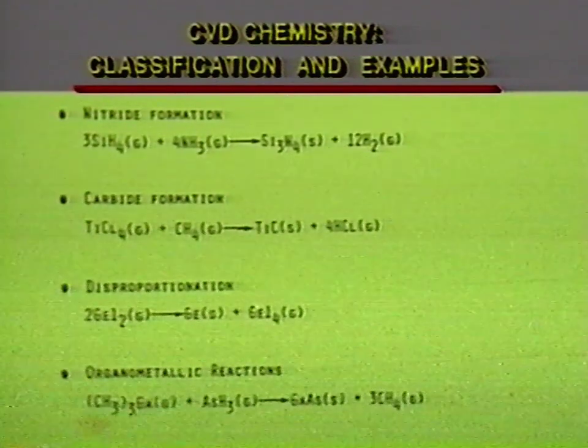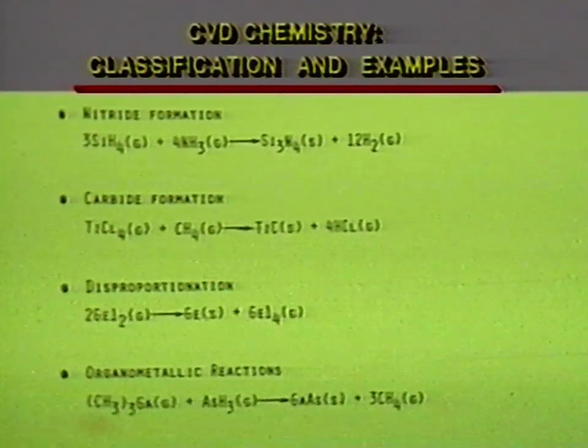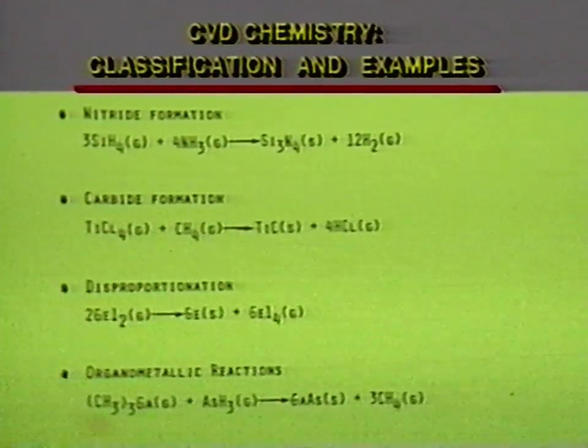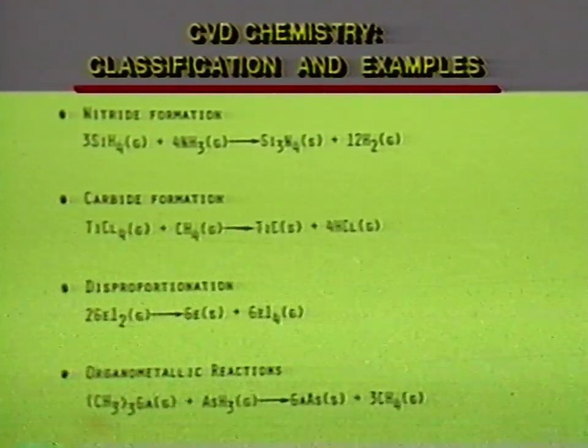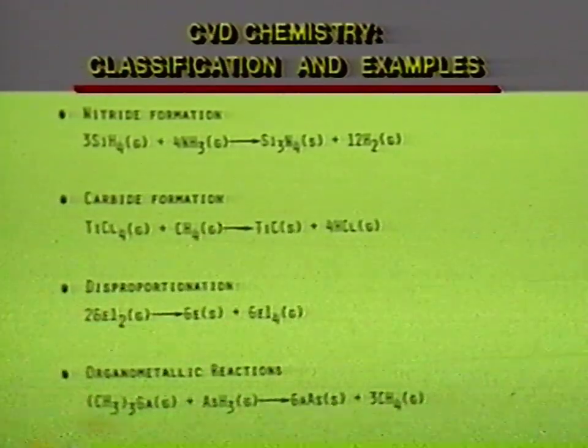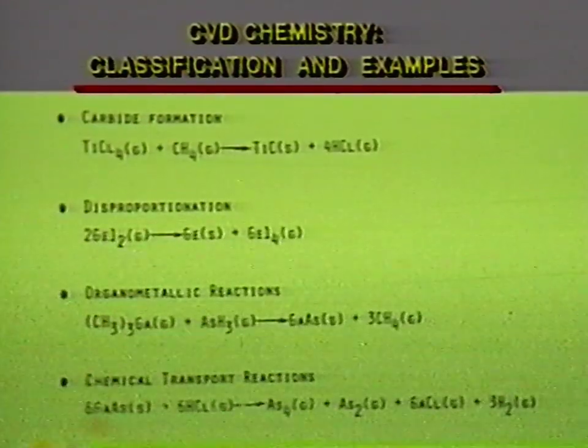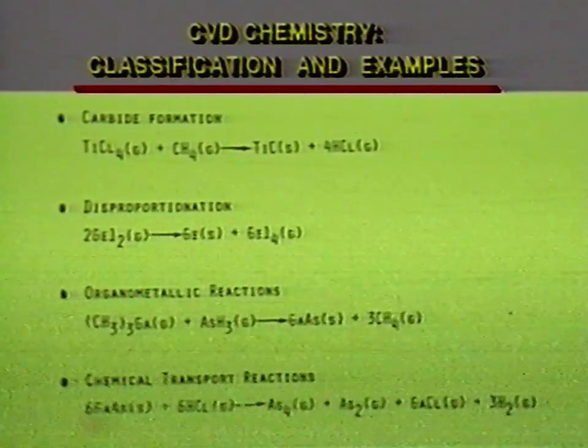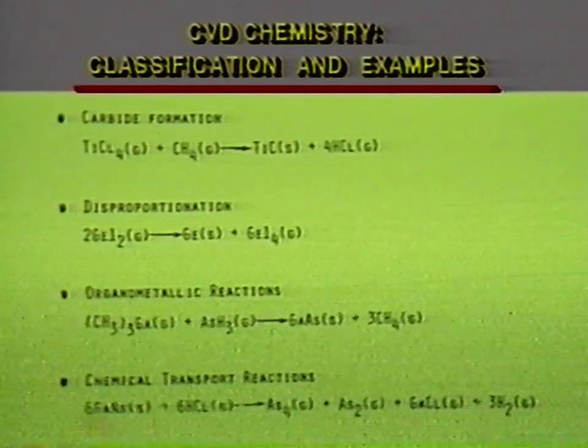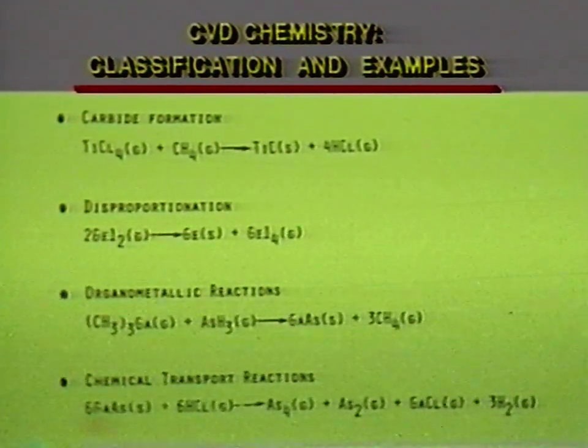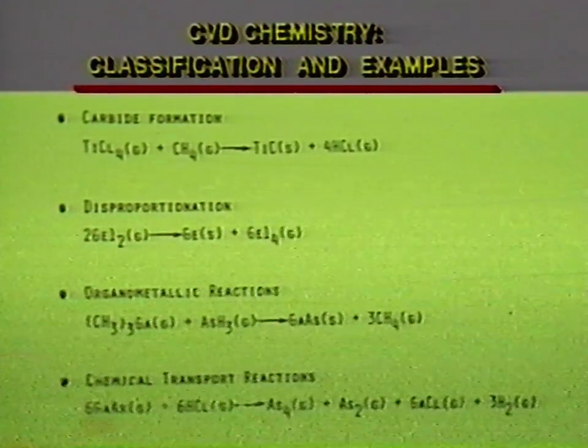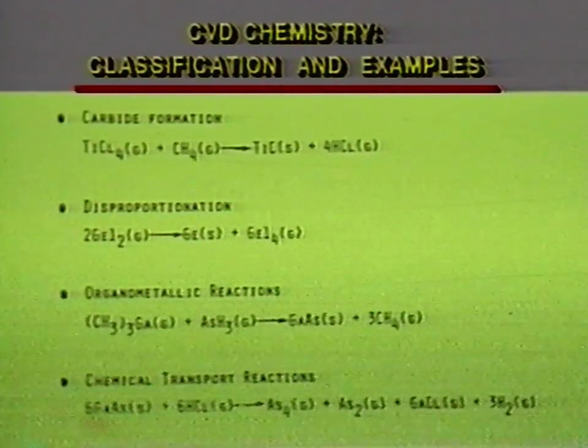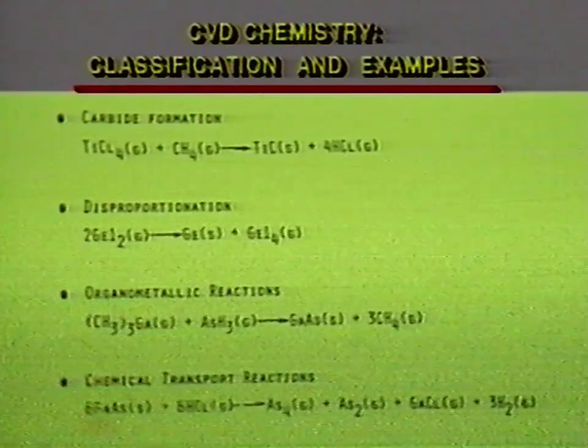About the organometallic reactions, which have become much more important recently for the synthesis of compound semiconductors. Here we have trimethyl gallium reacting with arsine to produce gallium arsenide and methane. And finally, transport reactions, where we transport one material with a suitable transporting agent, such as HCl or water vapor, into another. And here I have gallium arsenide shown with HCl to produce various species of arsenic and gallium chloride. Again, this is a reversible reaction and will depend on the temperature of the system, which way it will proceed.